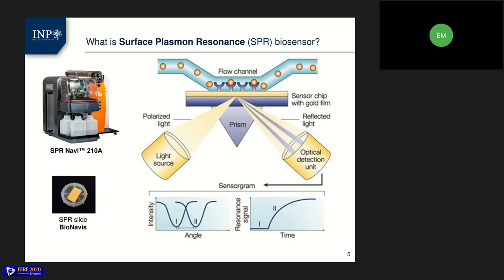The shape and the location of the SPR dip can be used to convey information about the sensor surface. So for the binding event between immobilized antibody and antigen from a solution, there is an increase of the angle of minimum reflection, and the SPR curve minimum is shifted. A sensorgram allows us to follow the changes of the angle of minimum reflection in time.